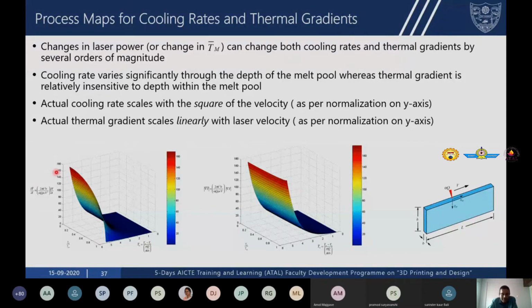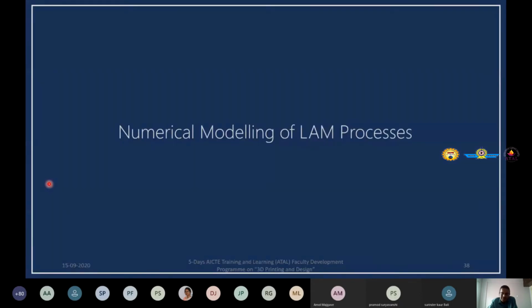Cooling rate varies significantly with the depth of the melt pool, whereas thermal gradient can be considered relatively insensitive to depth in the melt pool. The actual cooling rate scales with the square of velocity. It's more sensitive to velocity compared to thermal gradient, which scales linearly with velocity. And this is as per the normalization on the axis. Now I'm going to discuss finite element modeling of the LAM processes.